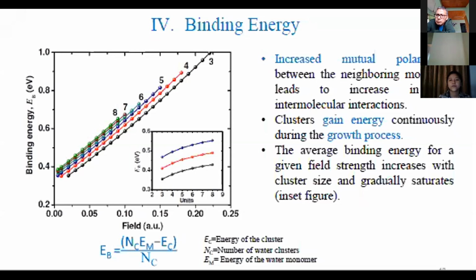But a closer look reveals that these 3 units, which is a shorter pentamer chain, can sustain its structure for a very wide range of field. Whereas 8 units can sustain its structure only for a narrow range of field. So though the system is gaining energy continuously, and its binding energy is increasing, we cannot say that the system is getting structurally favorable. So there is no strong correlation between the energetic stability and the structural stability of the system.